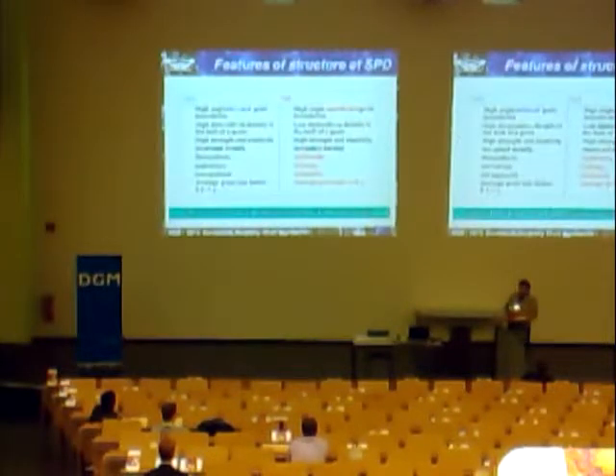A special interest is demonstrated in the schemes of continuous SPD, providing production of materials with modified strength-plasticity ratio in a quantity acceptable for commercial application. Undoubtedly, compared to cold SPD, hot SPD yields much larger grains in the deformed alloys, but such deformation allows formation of ultrafine, homogeneous, isotropic, and uniaxial grains, with dominating high-angle boundaries and low density of dislocations in the bulk.